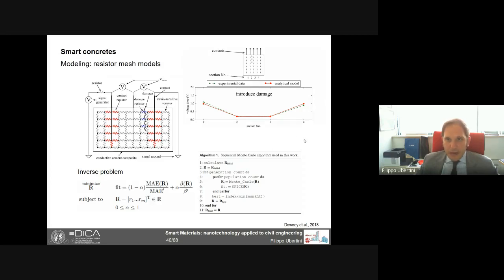Then if we apply a damage, we apply a crack, there is no match unless in the model we include the damage exactly where it is. If you look at the top, you see the real damage in green. It's a crack. It's actually a cut. And in red, we see where we simulate the damage with our model.